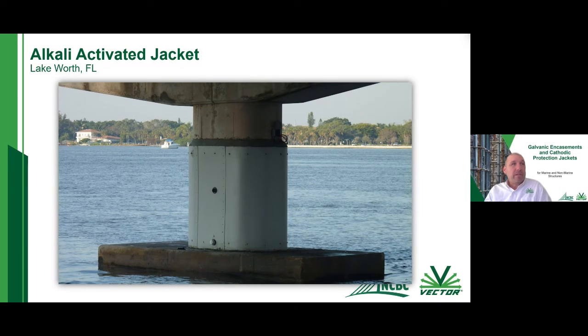So then here, this is after the mortar had been pumped into the jacket, and it was set and the forms were removed, and you can see the pumping ports on the sides of the jacket there, and the junction box is still open, so they were coming in and energizing the jacket system. So basically turning the jacket system on and verifying that they're getting cathodic protection out of this jacket system. So again, this jacket here does not rely on salt water. It only is relying on the activating mortar that's surrounding those anodes within that jacket system.